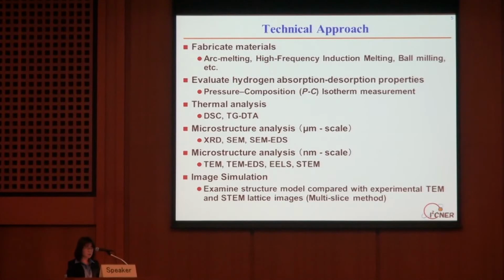In our study, materials are fabricated by arc melting, ball milling, etc. Hydrogen absorption-desorption properties are measured by a pressure composition isotherm apparatus. Phase composition, average crystal structure, and chemical composition are determined by XRD, SEM, and SEM-EDS. The structure of lattice defects and lattice strain, and the local distribution of chemical composition, are observed by TEM and scanning transmission electron microscopy, STEM. We can examine our structure model by comparing simulated images to experimental TEM and STEM images.